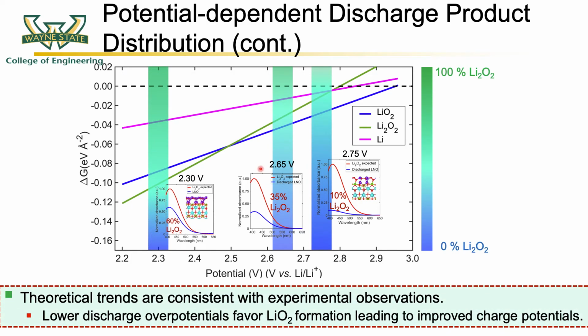While when one goes below 2.5 volts and discharges a cell at roughly 2.3 volts, 60% of the discharged product can be attributed to the formation of Li2O2, with only 40% being LiO2 now.